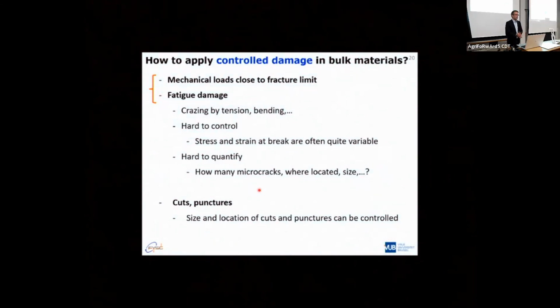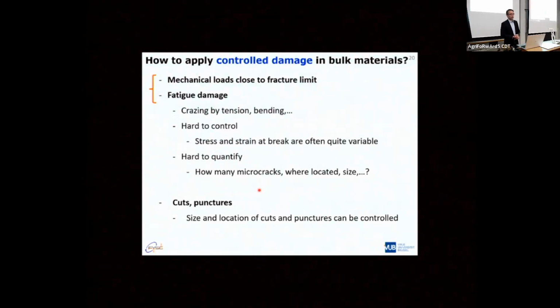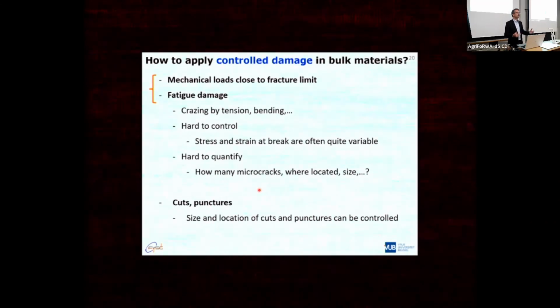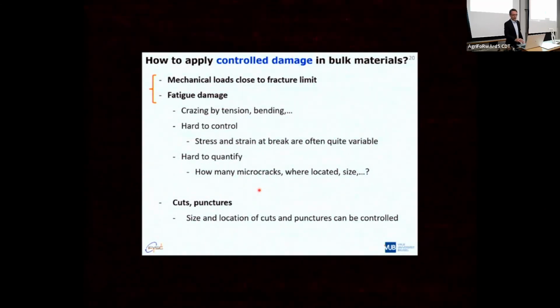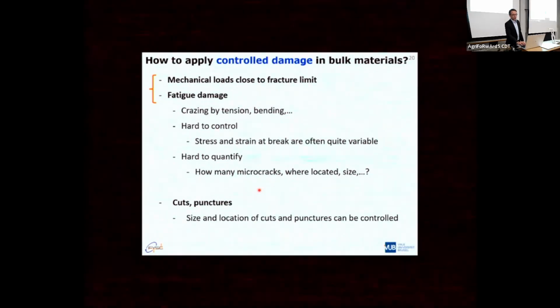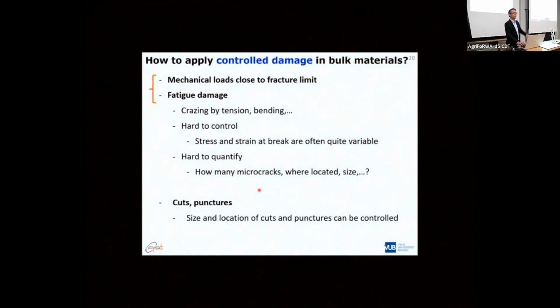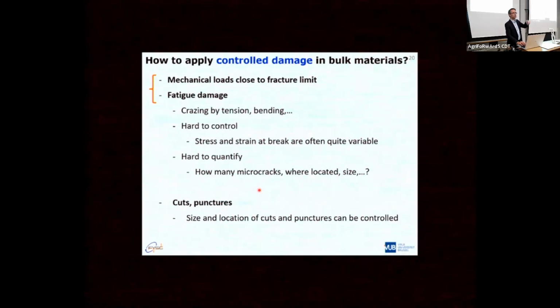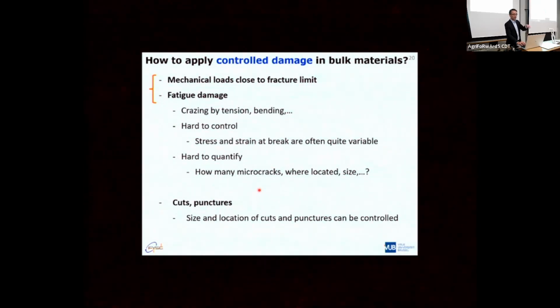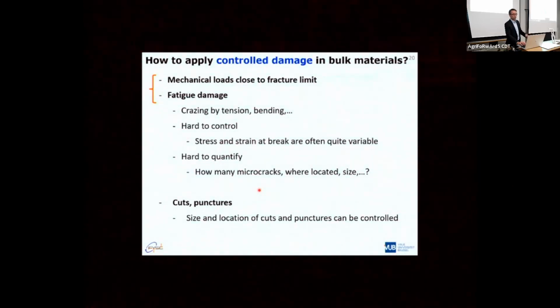You can try to have dyes migrating, for example, into the polymer and accumulating in the damage, and then use imaging techniques to find out where they are located and so on. But you can imagine that that's not something that you would like to do in series for large numbers of samples and so on. For the cuts and the punctures, it's a bit easier. You can do what Seppe did. You take the same type of scalpel every time. You push it through the material, and if you do it maybe with a controlled speed, if you really want to do it very nicely, you will make almost the same type of cut each time you do it.